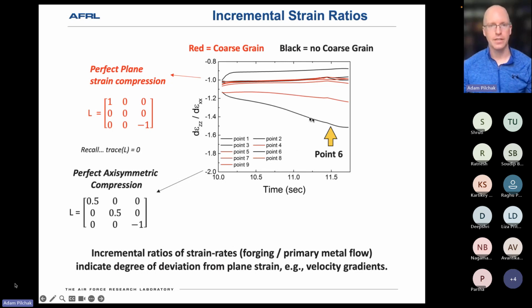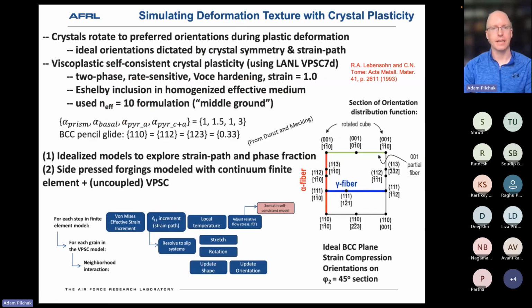But my point 6 here is the interesting one, where it deviates considerably from the case of perfect plane strain compression, meaning that there was axial flow in that material element as well, and it did not show any abnormal grain growth, and I believe that's due to its impact on texture evolution.